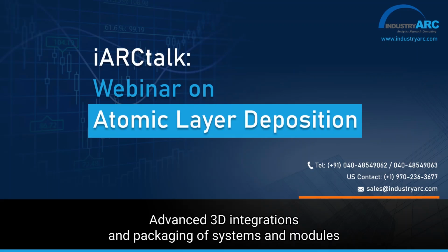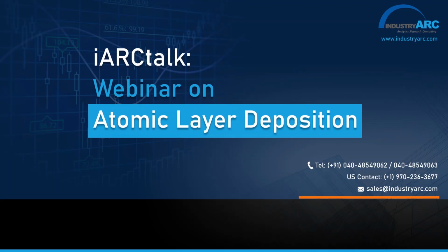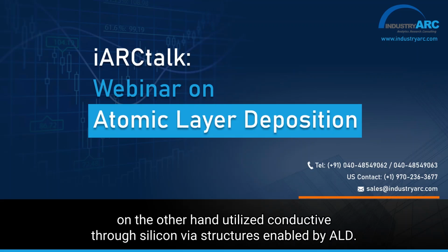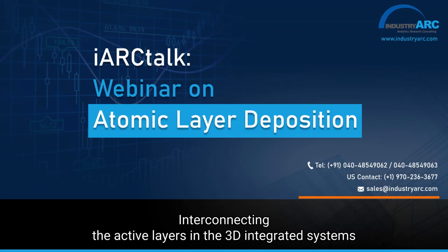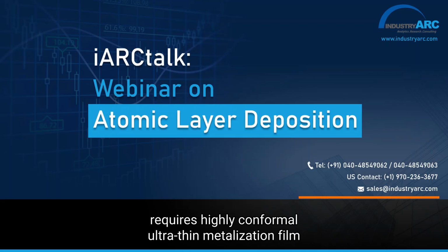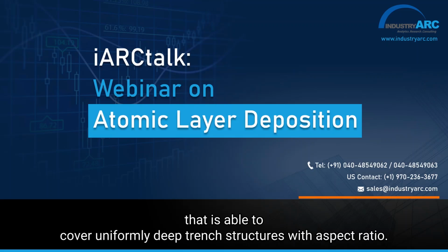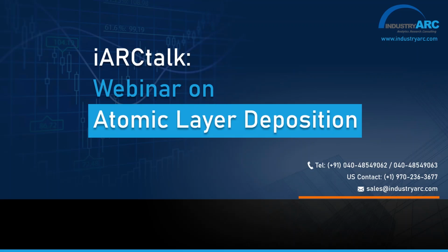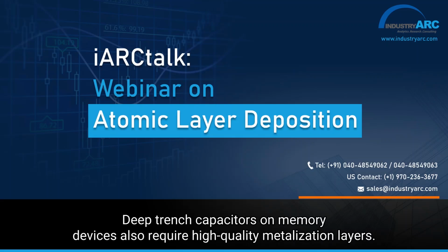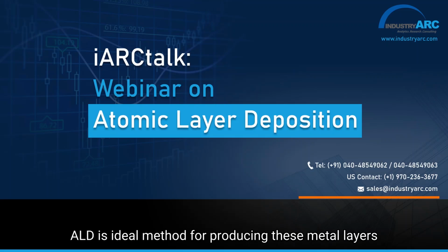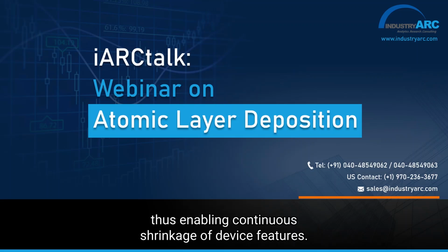Advanced 3D integration and packaging of systems and modules, on the other hand, utilize conductive through silicon via structures enabled by ALD. Interconnecting the active layers in the 3D integrated systems requires highly conformal ultra-thin metallization film that is able to cover uniformly deep trench structures with high aspect ratios. Deep trench capacitors for memory devices also require high-quality metallization layers. ALD is an ideal method for producing these metal layers, thus enabling continuous shrinkage of device features.